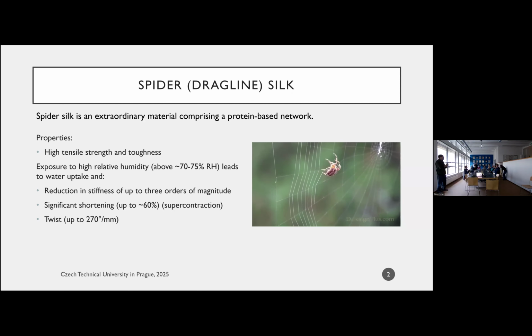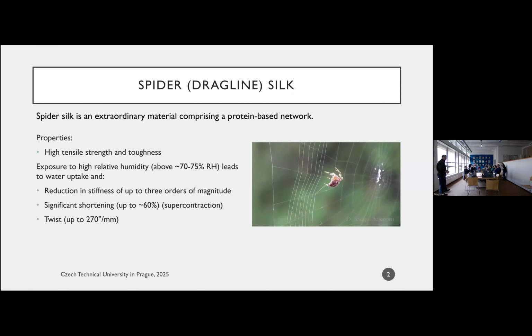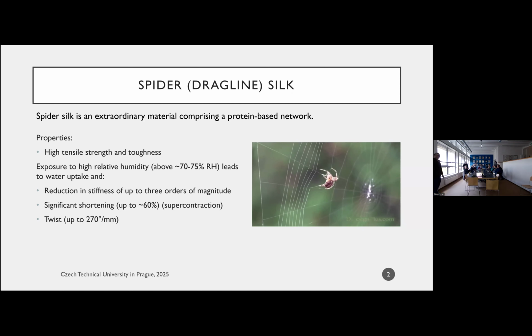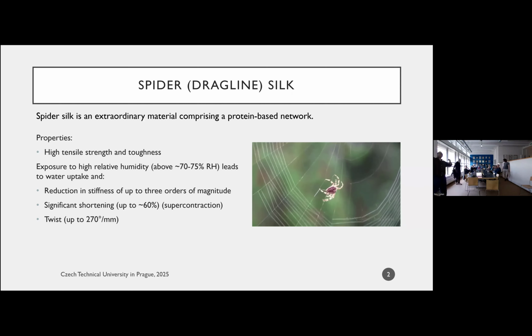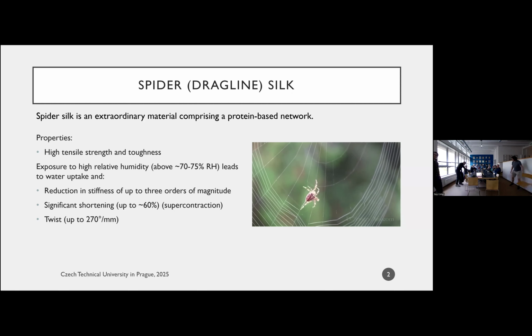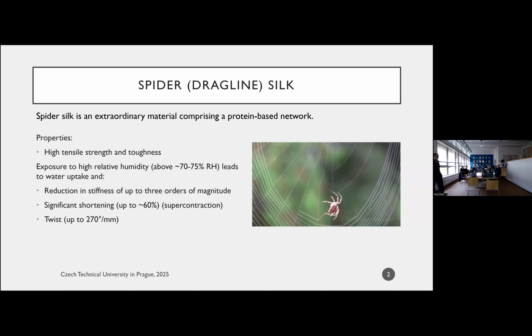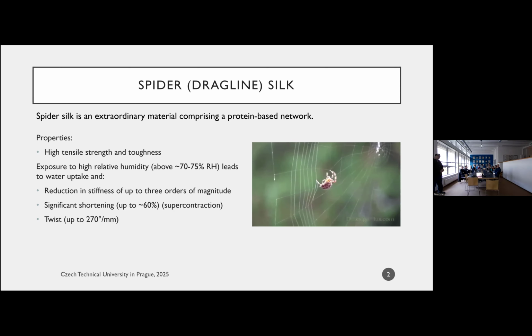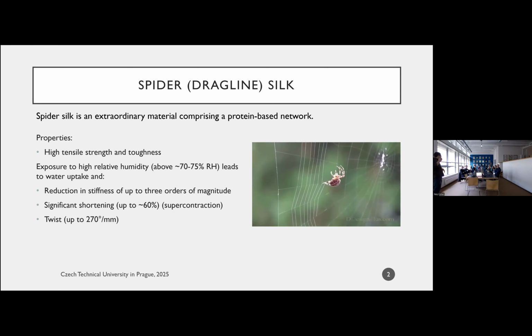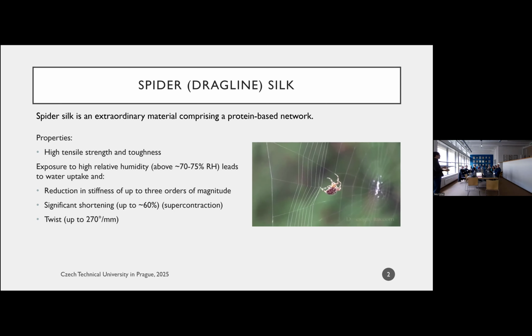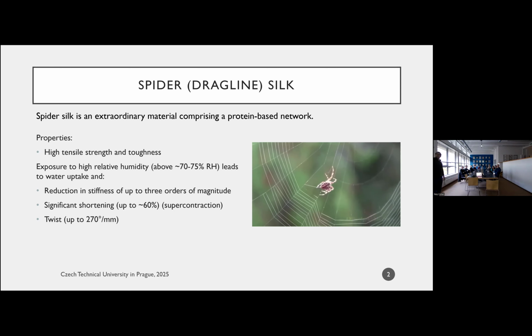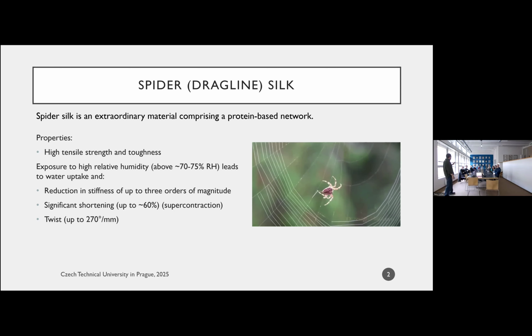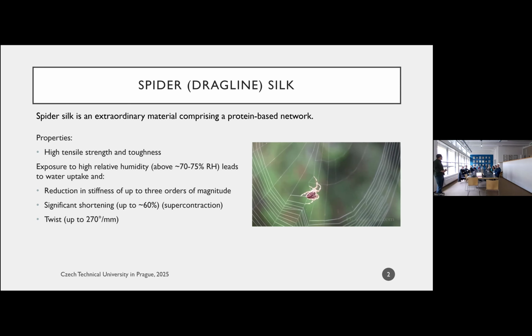Okay, so spider silk, if you're not familiar with it, is an incredible material. I'm sure you've all seen the famous spider web, and this guy here is just happily weaving a web, completely oblivious to the fact that the fibers he's weaving have extraordinary properties. So spider silk fibers are made of a protein-based network, and these materials have very high tensile strength. They're extremely tough, they're extremely stiff. And in fact, if we compare the strength to weight ratio of these fibers, it turns out that they can outperform even steel wires by about a factor of 5. So they're very impressive and they generate a lot of interest in the community.